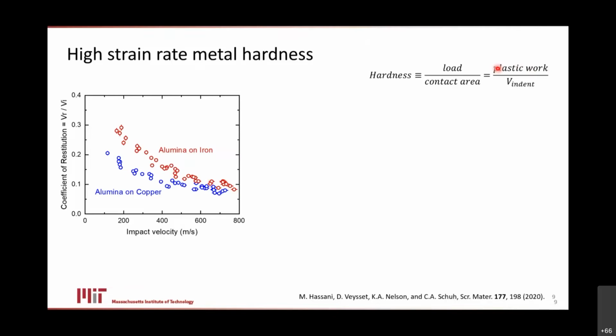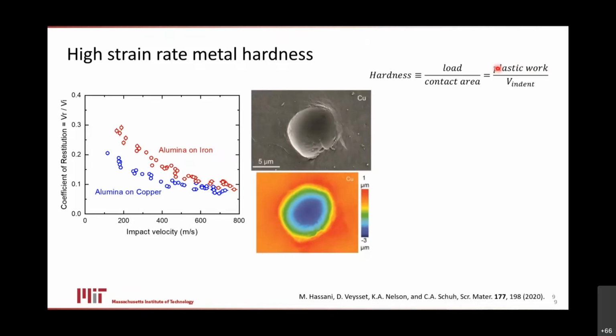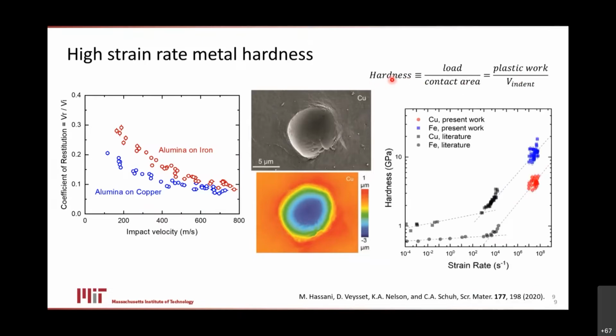And if you marry that now with some microscopy, you take this sample after you shoot it, and like a hardness test, you go look at it afterwards. And in fact, you don't just look at it, but you measure the damage you've done. In this case, we're using laser scanning confocal microscopy to measure very precisely the volume of that indentation. And if you know the plastic work and you know the volume of the indentation, that is literally the definition of hardness, which lets us extract hardness values. So we have now the hardness of copper here, the hardness of iron, with the notable exception that our hardness values are acquired at a strain rate of 10 to the 7th to 10 to the 8th per second. So extremely high strain rate, quantitative mechanical testing.